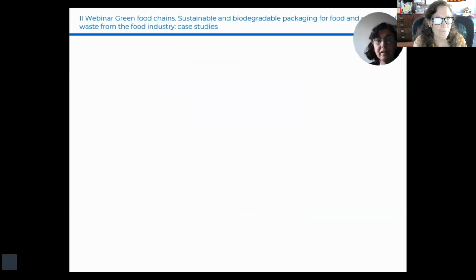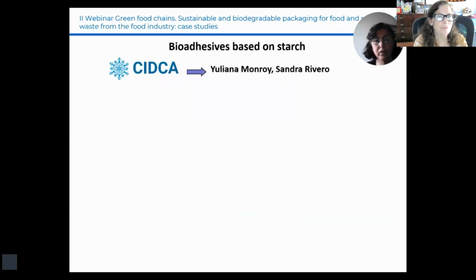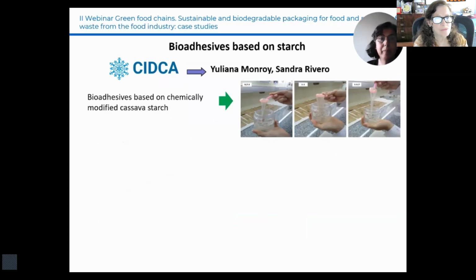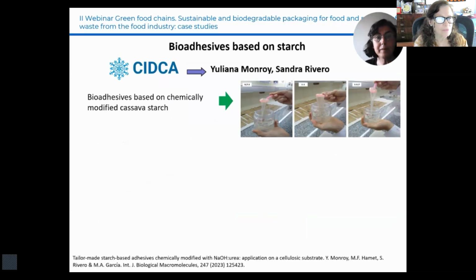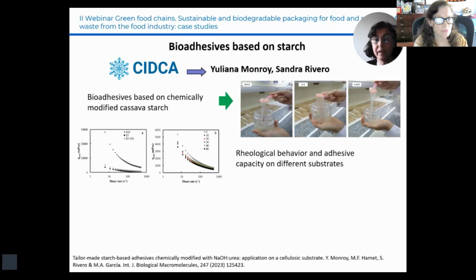On the other hand, as part of Dr. Yuliana Monroy's doctoral thesis, we developed a bioadhesive based on cassava starch chemically modified with polycarboxylic acids, such as citric acid and BTCA, as well as sodium hydroxide and urea. Optimizing the formulation allows us to control the rheological behavior and adhesion of the bioadhesive on different substrates.